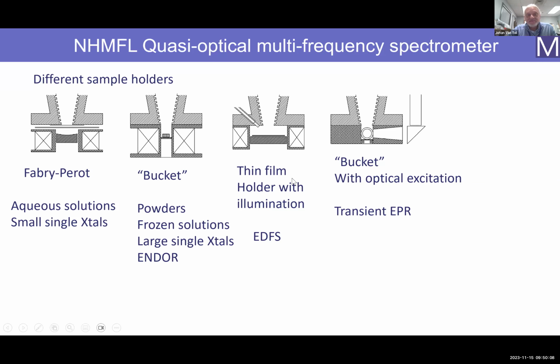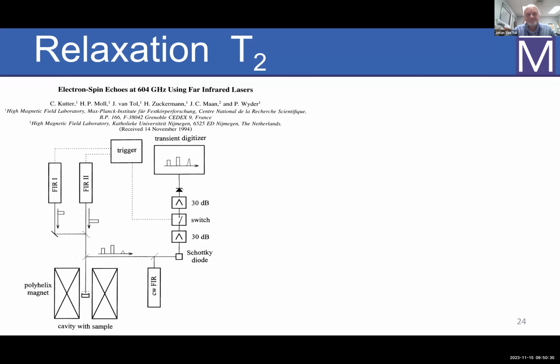You can make samples with thin films. So if you have thin films and you can provide some illumination to the thin films, I might give you an example if I have some. Oh, I'm running really late already. And then you also have a bucket resonator where you can excite optically with high power excitation to excite triplet states or transient for transient EPR.